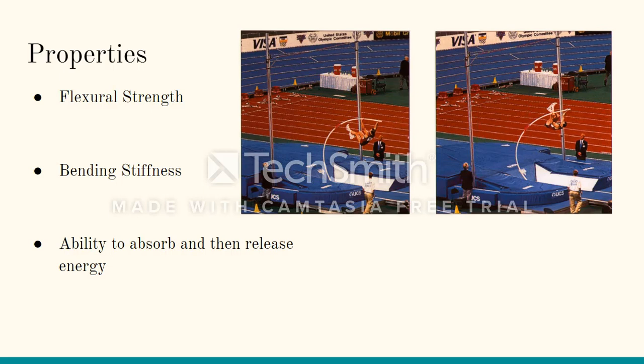The ability to absorb and then release energy factors in these two points. It is apparent that a balance must be found between stiffness and flexibility. Both materials must be able to absorb the kinetic energy of the runner and then release that energy safely and without failure. The reinforcing nature of carbon fiber allows for a quicker release of this energy, but the glass fiber allows for a more even and controlled release.